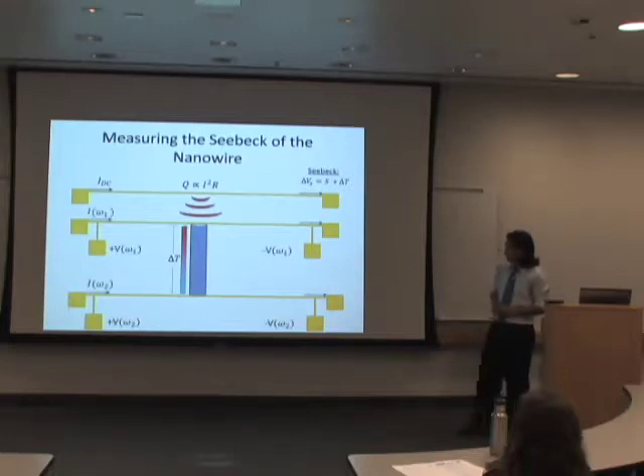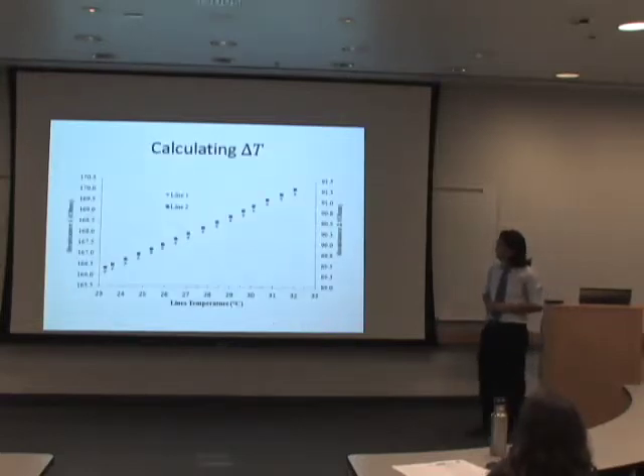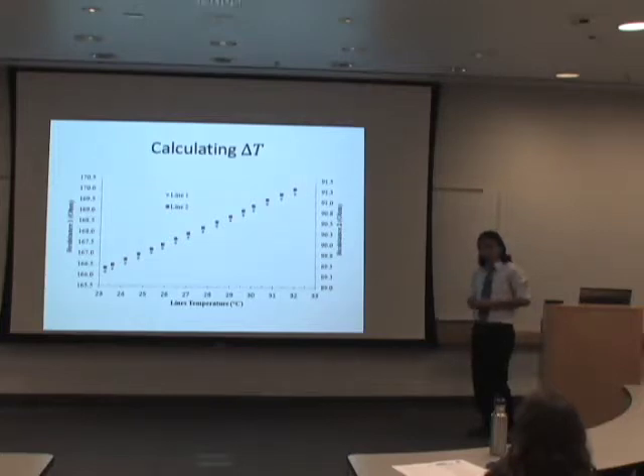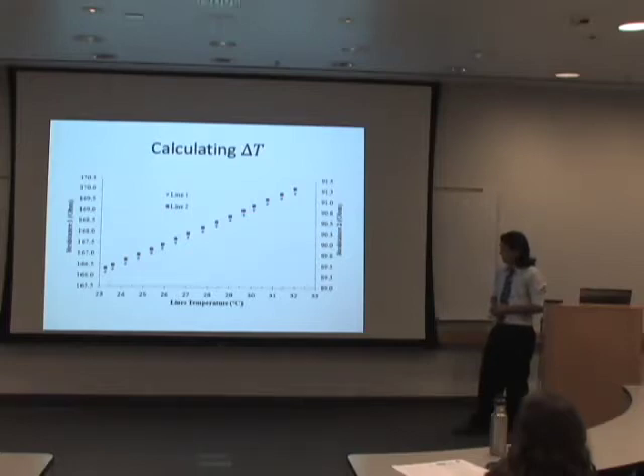And the way we do that is that we measure the difference in resistance before and after we apply the heat source. Resistance and temperature have a linear relationship. So to make it more clear, I have this graph, which we calibrate before making our measurements. As you see here, at room temperature the resistance on the line is about 166.5 ohms, and after we apply the heat source, maybe it changes, it goes up. So by knowing the difference in resistance, we can measure this difference in temperature.